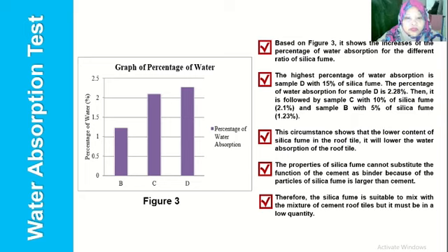Based on figure 3 here, it shows the increase in the percentage of water absorption for the different ratios of silica fume. The highest percentage of water absorption is sample D with 15% silica fume. The percentage of water absorption for sample D is 2.28%. Then it is followed by sample C with 10% silica fume, which is 2.1%, and sample B with 5%. Okay, let's proceed to the next test.